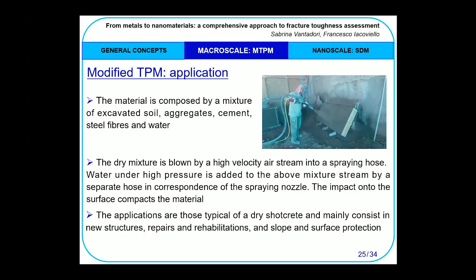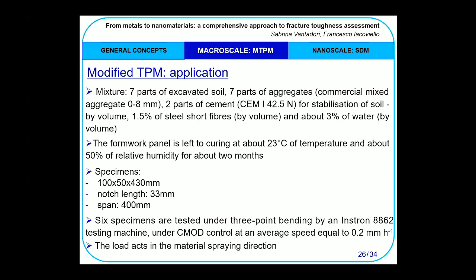The applications are those typical of dry shotcrete and may consist of new structures, repairs and rehabilitation, and slope and surface protection. More precisely, the material here examined consists of 7 parts of excavated soil, 7 parts of aggregate, 2 parts of cement for stabilization of soil, 1.5% of steel short fibers by volume, and about 3% of water. The formwork panel is left curing at about 23 degrees of temperature and about 50% of relative humidity for about 2 months. The specimens for fracture toughness evaluation are extracted from such a panel.